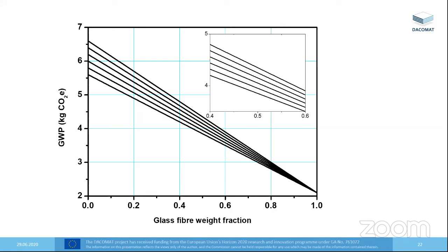When you start doing these sorts of analyses, you find that the differences in the environmental burdens, in this case the global warming potential, turn out to be quite insignificant compared with the whole of the lifetime. So we might find out that one single inspection of a wind turbine blade would have a greater burden in terms of the downtime of the wind turbine, the amount of energy that's gone into transporting whatever's needed to fix or inspect the wind turbine. We might find that has a much higher burden than this actual choice in the variation of the resin. But again, this is what LCA is for, to find out what's really important.